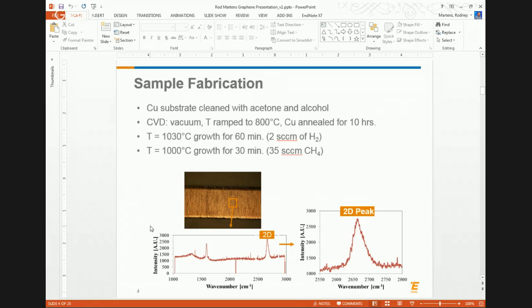So if you have a relatively sharp peak around 2700, that would indicate monolayer graphene. Now, as we get multi-layer graphene, that peak spreads out a little bit and shifts to the right, to the point where you get a very broad peak much further to the right if you have graphite, which essentially is just multi-layers of graphene.